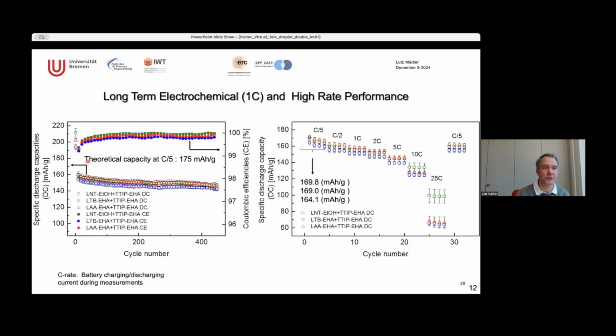And we tested it at different C rates for these different precursor combinations, for the ones that are phase pure. But they're not all the same. They look almost all the same, but there are really subtle differences, not so much in the specific discharge capacity, which is really, really good. It's almost 100% of the theoretical capacity. But at the high C rates, we clearly see a difference between our different precursor combinations.